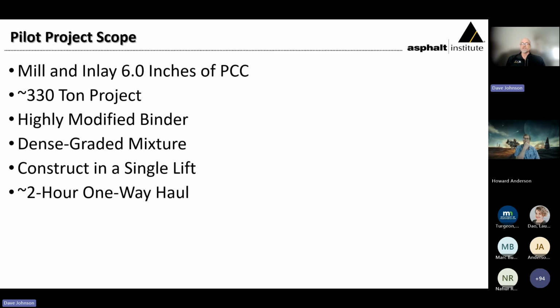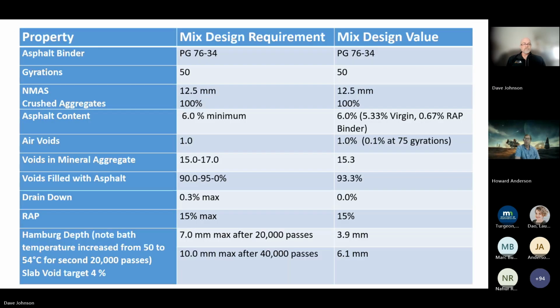So they were producing this material just north of Salt Lake City. The contractor was Staker Parsons, part of the CRH group, and they hauled it over to the Nevada border along Interstate 80, which takes them roughly 2 hours. You can see the mix design requirements calling for that 76-34 binder. Normally, this would have been a 75 gyration mix design, but as we see, they dropped that down to 50.